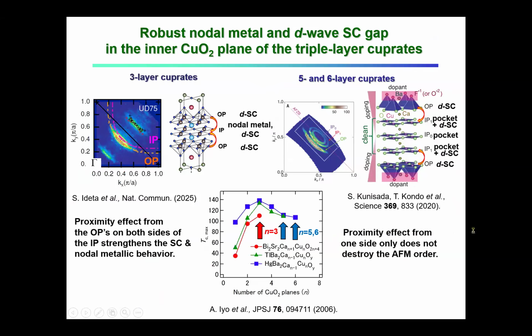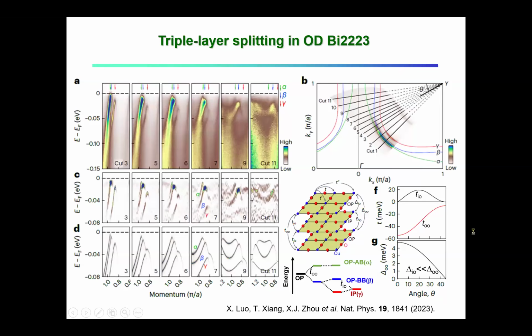You do find that there are two Fermi surfaces which are degenerate at the nodal direction, and then they split at the zone boundary. These are the outer layers, while the inner layer is separate and has basically no weight from the wave functions of the two other layers, and has a smaller volume. So that is what DFT would tell you, and that's what you find.